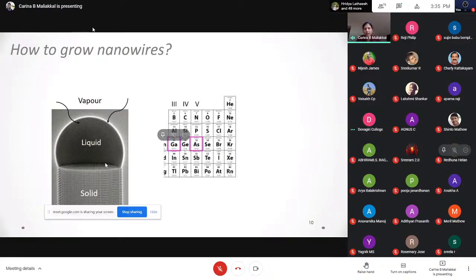Let us look at an example, if we are trying to grow gallium arsenide. Okay, so we want a gallium precursor and an arsenic precursor. Precursor just means that you're using a compound which, if given the ideal conditions, would decompose and give you the elements you want. So you use a gallium precursor and an arsenic precursor, you supply them in the vapor phase, and they dissolve in a liquid. Usually we use a gold based liquid, I'll come to it, and we put in sufficient temperature, and then we can cook up gallium arsenide.